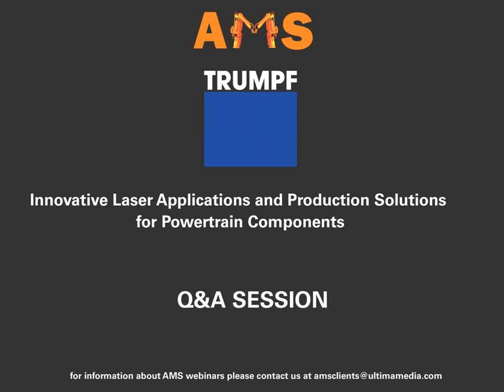Because if you see these production sites, for example, at Volkswagen, at Daimler, and so on, we have a lot of different stations there, because the laser weldings I showed in the presentation, you saw a lot of different weldings per double clutch. So we can use one single source with more than 2 or 3 exits for the fiber cables. So we can use one laser for 3 or 4 or 5 welding cells. This is more a question of the production philosophy. But nowadays, I would say, if you see the latest developments all over the world for the double clutches, this is solid state laser that is used for mass production.